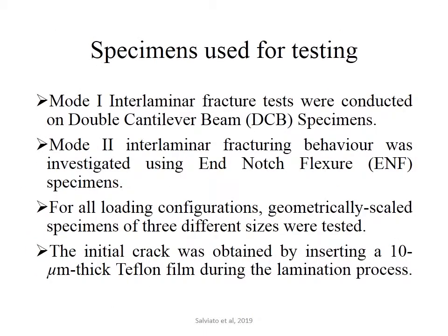These are the specimens used for testing. Mode 1 fracture tests were conducted on DCB specimens and mode 2 fracture tests were conducted on ENF specimens. They tested geometrically scaled specimens of 3 different sizes, with pre-cracks introduced by inserting a 10 micrometer Teflon film during lamination.